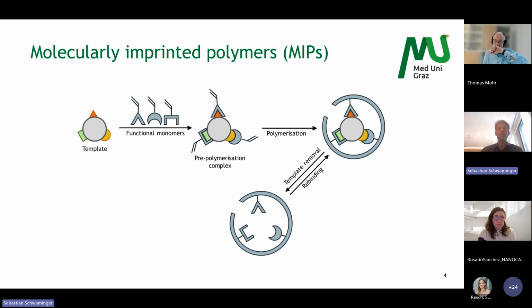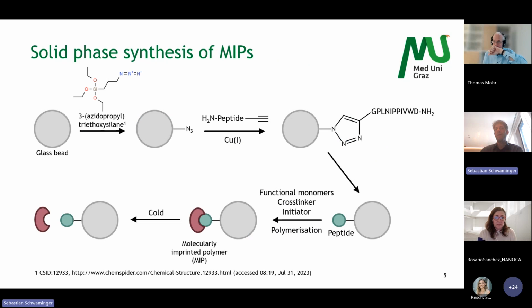We have the polymerization around our template, and with template removal and rebinding, we get our molecularly imprinted polymer. So we then have a polymer which we can use. In our case, we use glass beads. On these glass beads, we bind distinct peptides which resemble the receptor structures on the surface of tumor cells. With this peptide, we then add a cross-linker, initiator and the functional monomers, which are the counterparts to this peptide, and polymerize them.